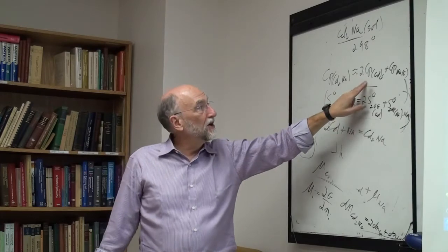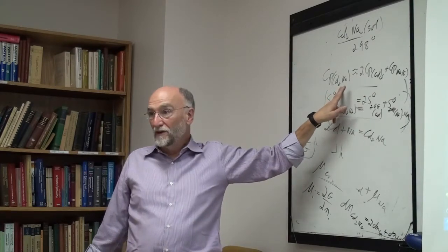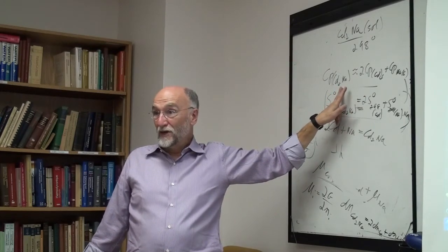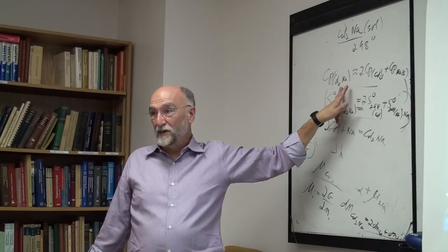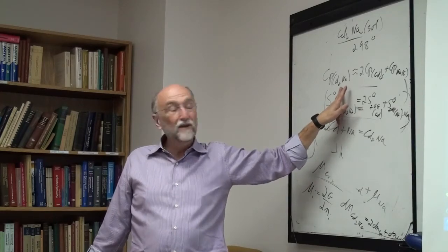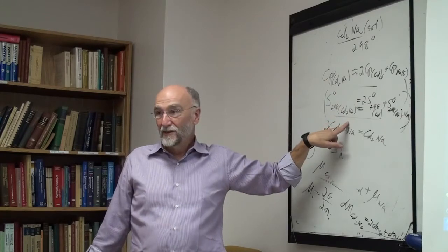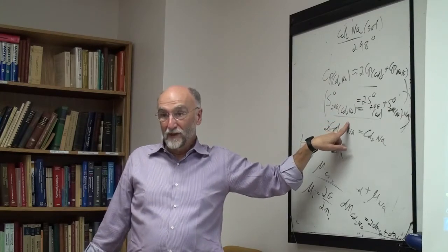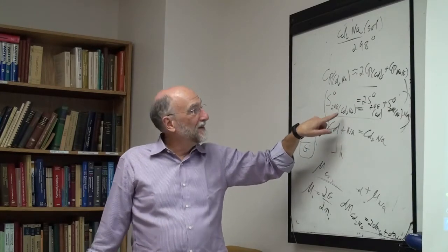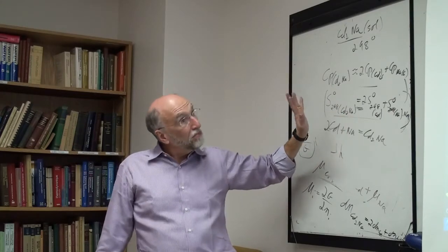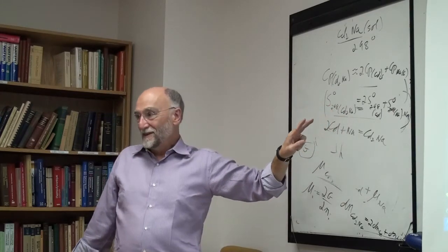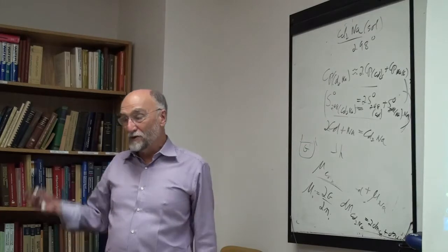Now, you might have an ordered solid, in which case the entropy would be positive or negative. The solids generally tend to be ordered, so you'd expect this delta S to be negative. Okay, so negative 10, positive 10, you'll see it, but you've got to think about orders of magnitude as well.